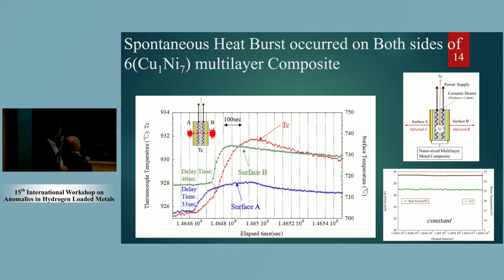And this is an example of spontaneous heat burst occurring on both sides of a 6(Cu1Ni7) multilayer, a multi-layer composite. In this case, this is the time, and this axis means the thermocouple temperature, the surface temperature. At this point, on surface A, a spontaneous heat burst occurred, and surface temperature increased. After that, at this time, on surface B, a spontaneous heat burst occurred. And they propagate to the center thermocouple. And we got this kind of thermocouple temperature time variation.